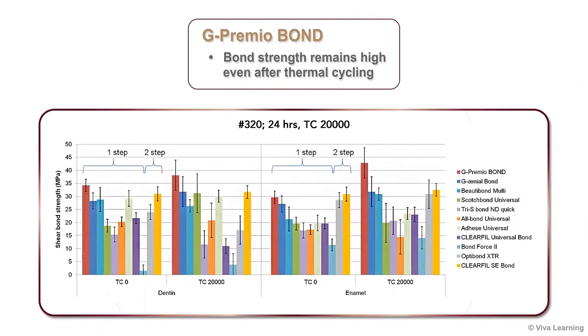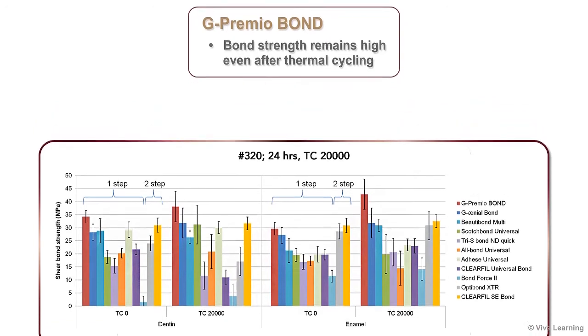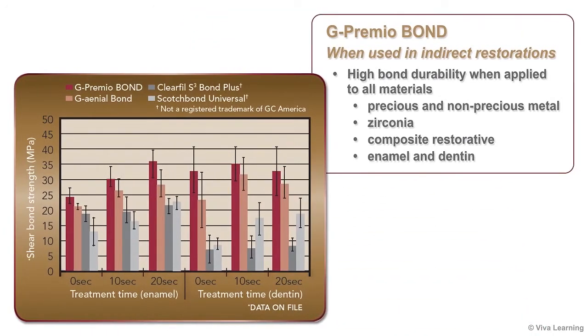And with G-Premio Bond, this bond strength remains high even after thermal cycling, whether the adhesive is applied directly to dentin or enamel. For indirect restorations, G-Premio Bond provides high bond durability when applied to all materials, including precious metal, non-precious metal, zirconia, composite restorative, enamel, and dentin.